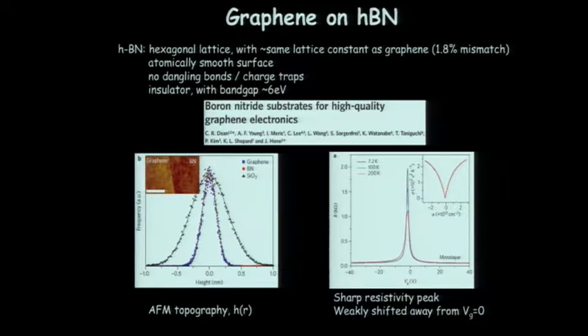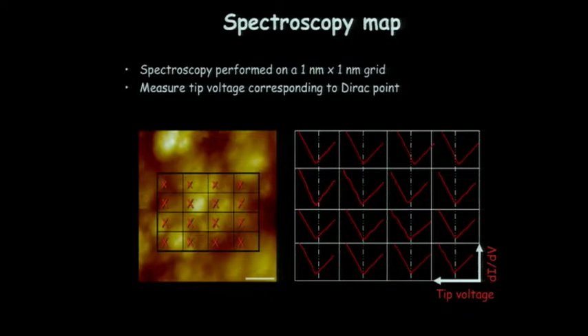But we want to actually go and look at this locally to see what's happening on the atomic scale. And so the way that we can probe this is by doing a spectroscopy map over the substrate. We go to each position on the sample, and we take one of these dI/dV spectra. And so these dI/dV spectra can tell you about the doping in the sample just by where the minimum is. The minimum in the spectra is occurring at the charge neutrality or the Dirac point. And as you move to different locations, those minima shift. Here it's a little bit to the left side. Here it's neutral. Here it's to the right side, etc. And so we just map the shift of this Dirac point as a function of position in the sample. And that tells us something about the charge disorder in the sample.